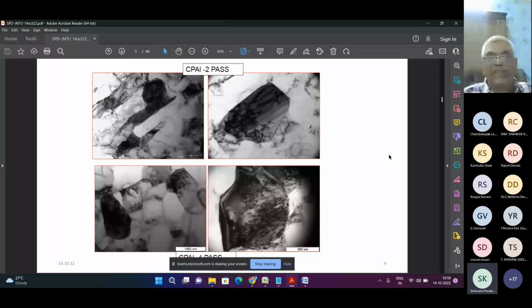Still, you can see that even though grain refinement has taken place, some of the grains are elongated in nature. When you have gone for 4 passes, you can see that it has been reduced. I think the bottom one should be the four pass image, where you can see that grain sizes are almost uniformly becoming round in shape, not exactly round, but similar to a round shape.